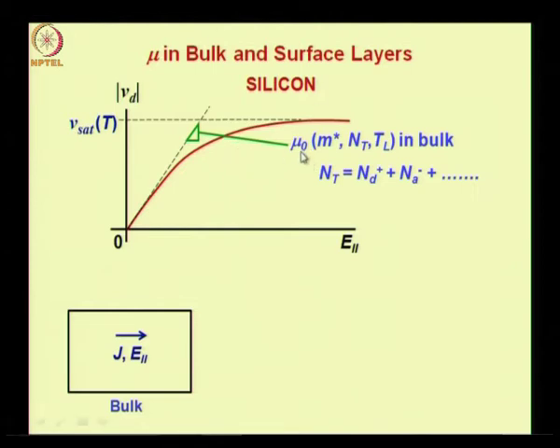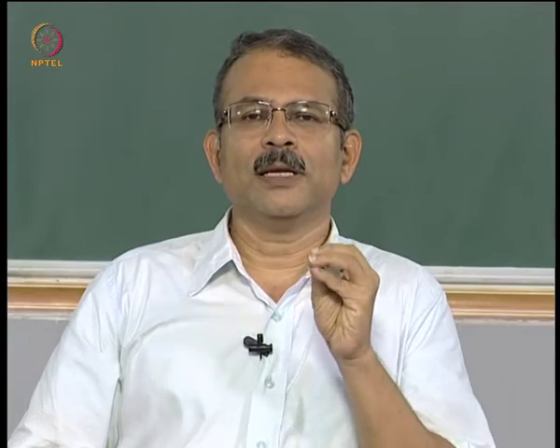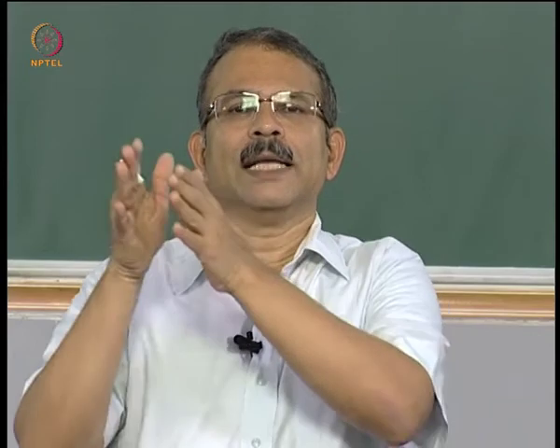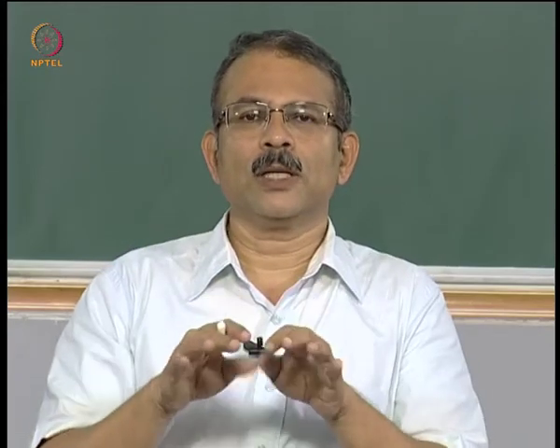Now the low field mobility is a function of the effective mass of carriers, the total doping, total number of ionized impurity atoms, which is the sum of the positively charged ionized impurities and negatively charged impurities, right. So this is important to note that the mobility depends on the sum total of all the impurities, donors, acceptors, traps and everything. This is unlike the carrier concentration. The majority carrier concentration depends on the net impurity concentration, that is the difference between the donor impurity concentration and the acceptor impurity concentration, whereas the mobility depends on the total impurity concentration.